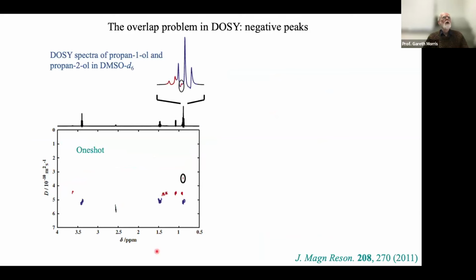Okay, so let's do a fairly standard experiment with just a slightly longer, slightly wider gradient pulse than normal. And we see here that where we've got our nice wide methyl multiplet, we get a little bit of J modulation, so we get a little bit of negative signal. But now if this negative signal overlaps with a fairly small positive signal, we can get an apparent diffusion coefficient, which is way out.